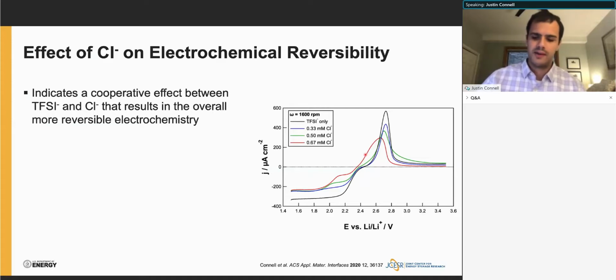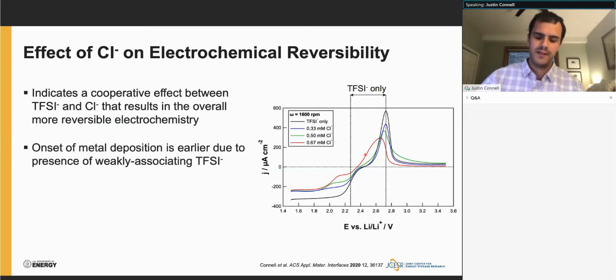And to illustrate what I mean by that, we can return to this idea of there being essentially two overlaid redox couples, where if we highlight the TFSI-based contribution to the voltammetry, we see the early onset of metal deposition, but a higher overpotential for metal dissolution. And why we believe the deposition is able to initiate earlier is due to the relatively weaker association strength of TFSI with the zinc cation. And so it essentially takes less energy to desolvate zinc from a TFSI-rich coordination relative to chloride.